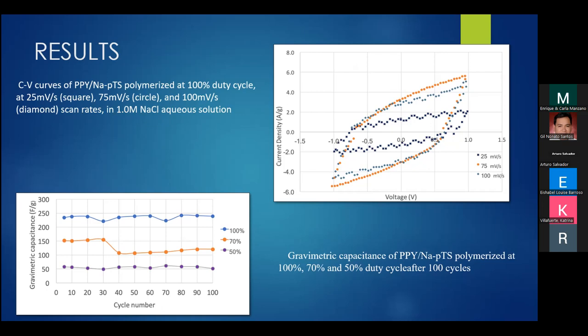to the other films grown at 70% duty cycle and at 50% duty cycle. For the other films, they deteriorated somewhat; their specific capacitance decreased to 89 to 90% after 100 cycles. But for the film grown at 100% duty cycle, the capacitance is relatively very stable after 100 cycles.